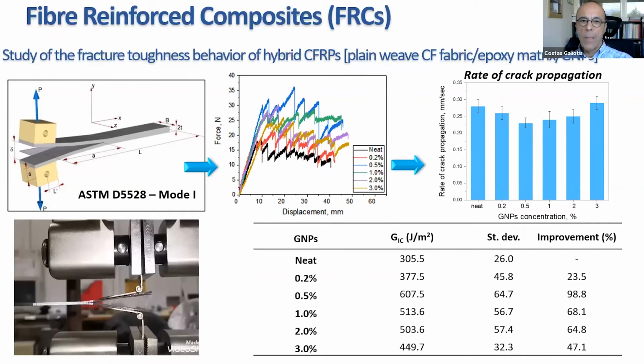the fracture toughness. And what happens is that a crack that tries to propagate within the material comes across a graphene layer and then it deflects. And that of course consumes energy. And this improvement is quite important, you will see here. But if you carry on, and this is what we found in many cases, and you increase the content, because of agglomeration, you lose this profit, this gain, so to speak. So less the better, and it's of course less expensive.